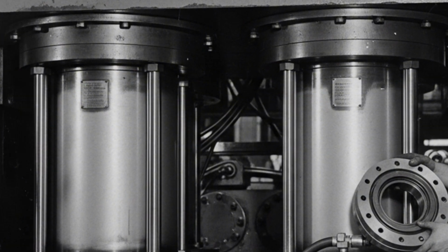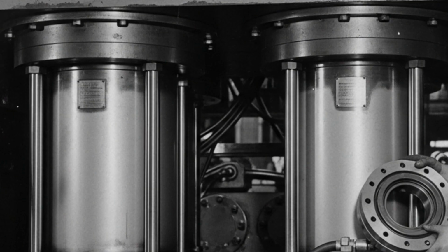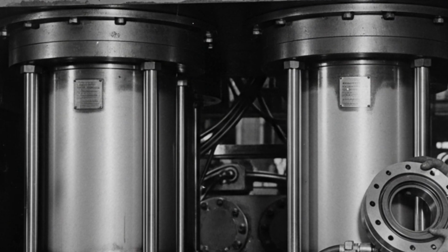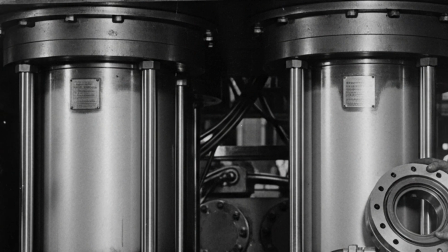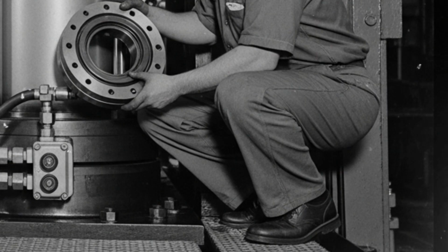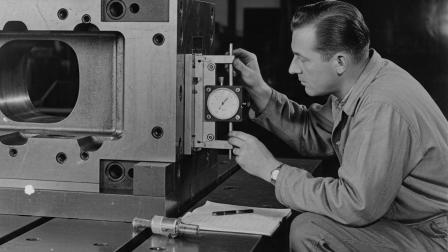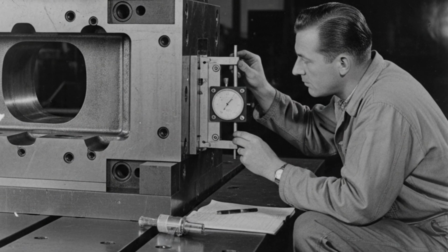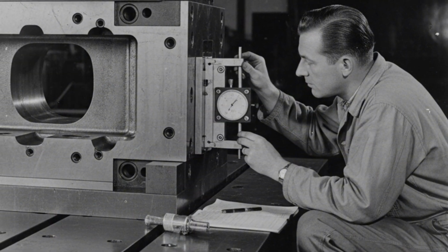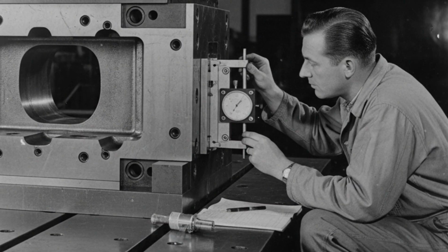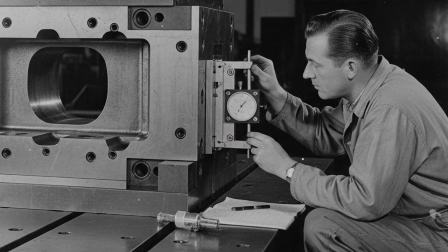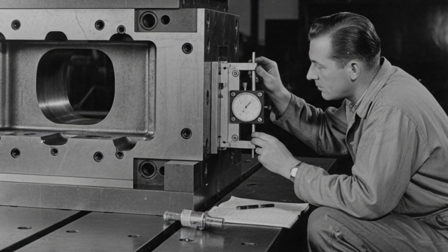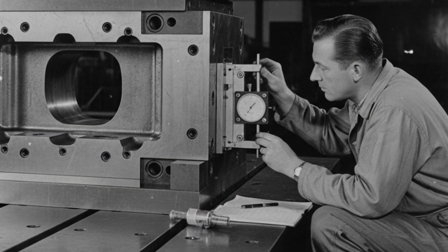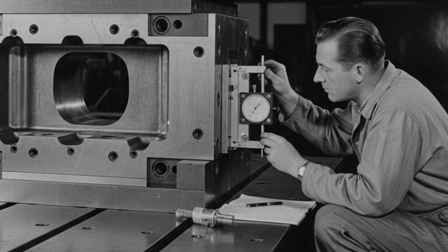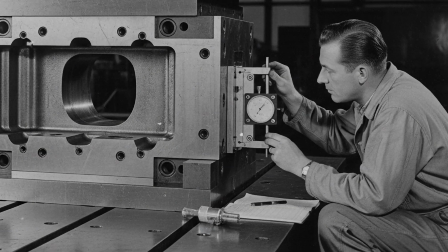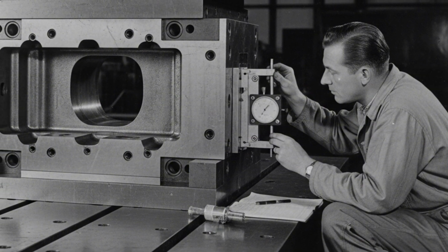A seal failure at operating pressure does not produce a slow leak. No, it produces a hydraulic fluid release at pressures sufficient to cut through unprotected human tissue with the efficiency of an industrial cutting tool. The third system is the die set and bolster assembly. The bolster, the massive steel table on which the lower die is mounted, is itself a precision-machined component, typically weighing between 20,000 and 60,000 pounds depending on press size, and equipped with a hydraulic die clamping system that must hold the lower die in precise registration under impact loads that occur at the moment of forging contact.